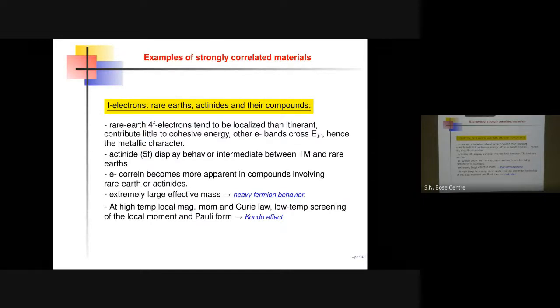And electron correlation becomes more apparent when you mix some rare earth with something like aluminum, some compound. Then it becomes even more important. This is reflected in extremely large effective mass, which leads to heavy fermion behavior, which shows phenomena like the Kondo effect, where you have a local magnetic moment that arises out of this f electron, and other electrons that give rise to a conduction band. Below a certain temperature, this local moment can get screened by this conduction band. That's your Kondo temperature. Above the Kondo temperature, this local moment shows up because the screening becomes weak.